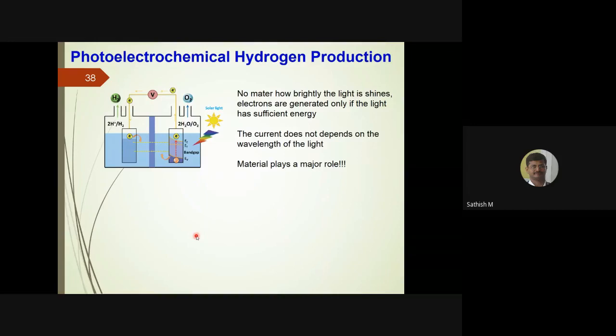for photo based processes. Okay, this is not only a hydrogen process, it's a hydrogen production. You can make a hydrogen production at one side. The other side you can use an oxidation reaction. The oxidation reaction is not necessarily the oxygen evolution. Okay, instead of oxygen evolution, you can use some pollutant. The pollutant will be getting oxidized. Essentially, what you need is you should get both oxidation reaction and reduction reaction to take place. Then only the overall reaction will take place.